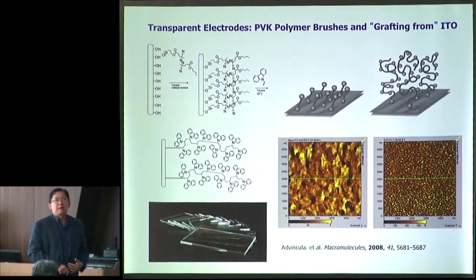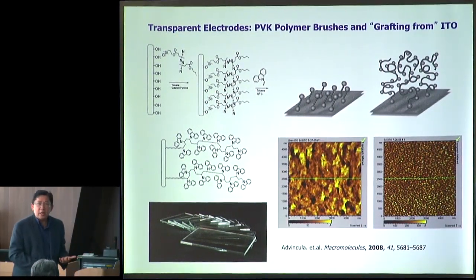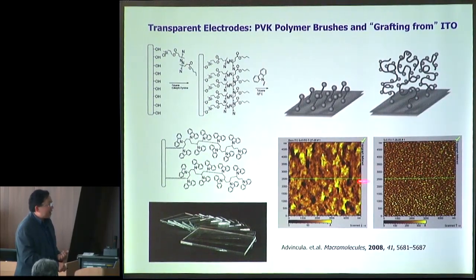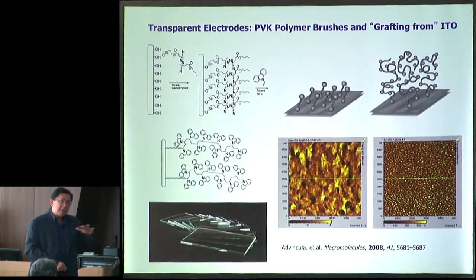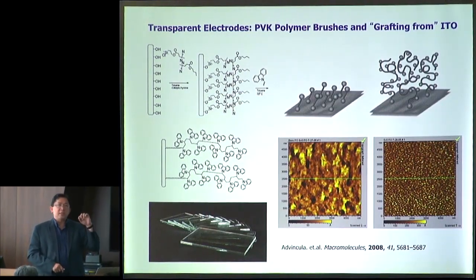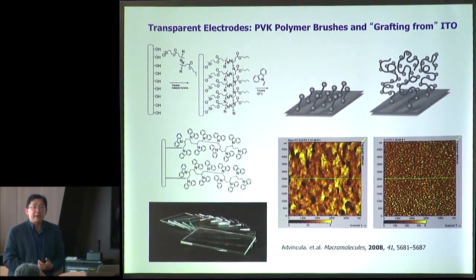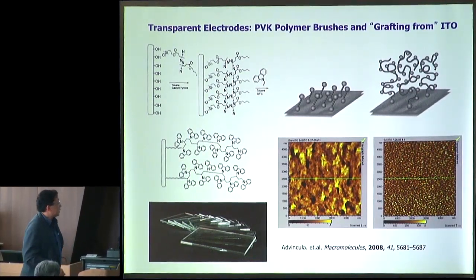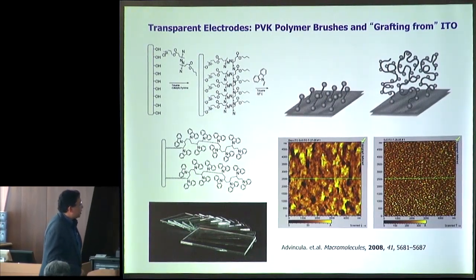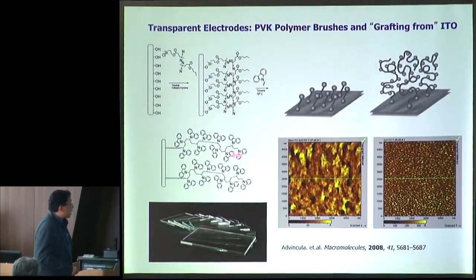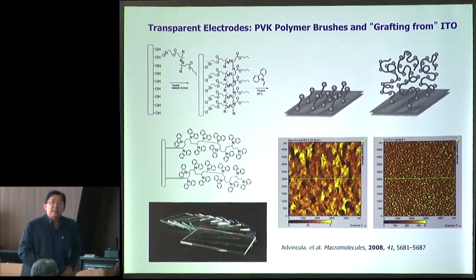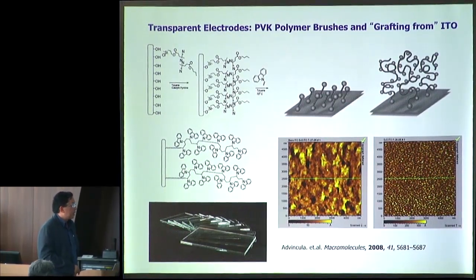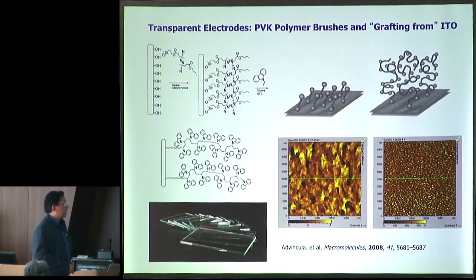You need to, for example, put a self-assembled monolayer. In our case, we actually grew polymer brushes. So we grew the polymer brush on ITO, and after growing polyvinyl carbazole, for example, we get this smooth, nice film. Not only is it smooth, planarized, but it also improves the hole transport layer properties in an LED material, such that after we have added it and cross-linked it on a surface, we can actually get very efficient devices, both LED and photovoltaic devices.